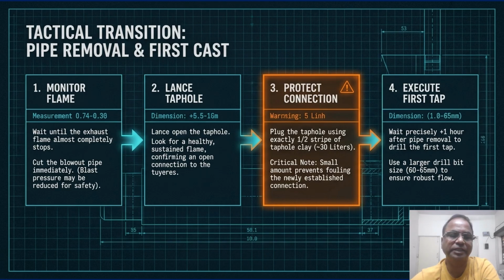Step 3 is highlighted in orange, that is protect the connection. You must plug the taphole using exactly a half strip, roughly 30 liters of clay. Any more will foul the connection we just worked to establish. So finally, step 4, execute the first tap exactly 1 hour after pipe removal. Use a larger 60 to 65 millimeter drill bit. The so-what factor here is establishment of a stable tapping rhythm. Get this right and you have successfully transitioned the furnace from a construction project to a production asset.